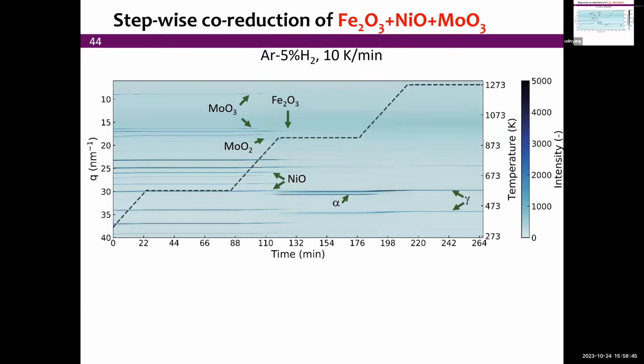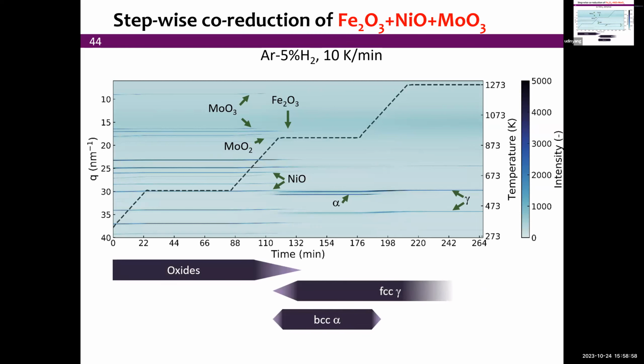And now we make it a little bit more complicated. We have molybdenum oxide, which also can be reduced. And now we see new peaks for moly trioxide, moly dioxide, and eventually we don't see even moly, it goes directly into the iron nickel. So we're really going from oxide to BCC iron again to FCC gamma. This is now almost steel at this point. So we can print from individual oxide particles and end up with a co-reduction step associated with interdiffusion, ending up with a fully alloyed structure.